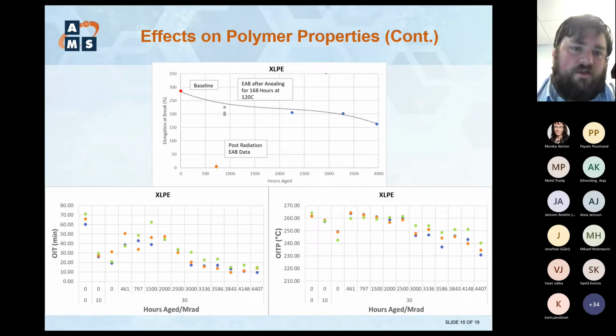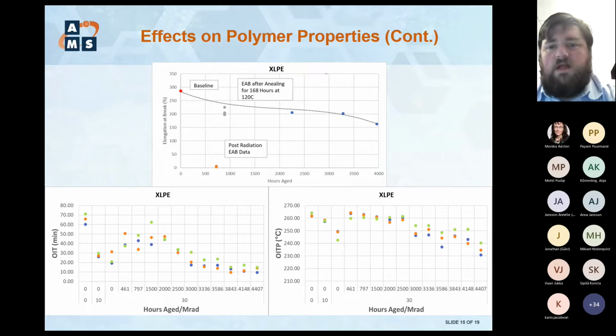You can see from baseline, this XLPE sample, a semi-crystalline sample, has this huge decrease in EAB, but a huge amount of recovery after 168 hours of thermal annealing at 120 C. Interestingly, we saw similar behavior in our oxidation induction time and temperature measurements. And some of our electrical results also showed that too, where you actually get this decrease, recovery, and then more of the typical OIT, OITP decreased behavior you would expect.